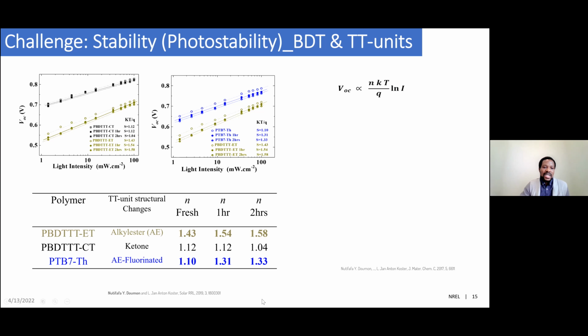And here clearly you can see that when we take the most stable, which is the ketone-based device, the ideality factor did not change much over time. So it remained very constant. That could explain why the devices perform well under photo-induced stresses, which means that there is no increase of charge trap-assisted recombination in the system. As compared to the other ones, you can see that there is an increase. Well, this increase is not directly correlated to the amount of traps in the system, but at least it indicates that there's an increase in trap recombination in the system.